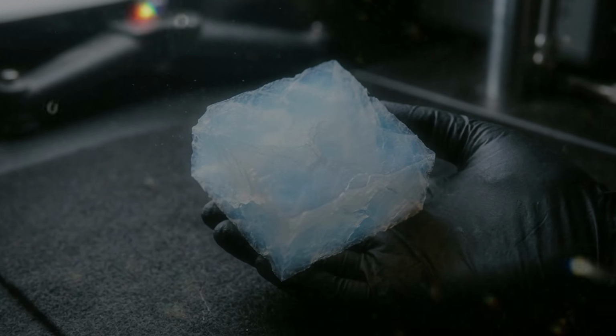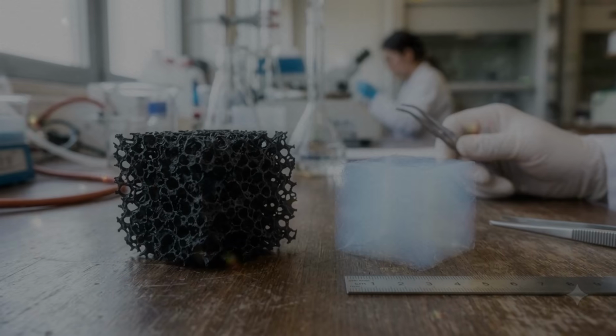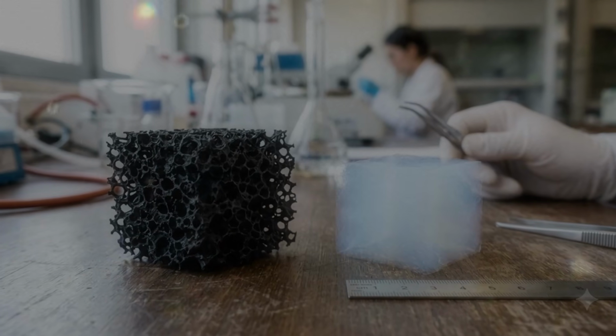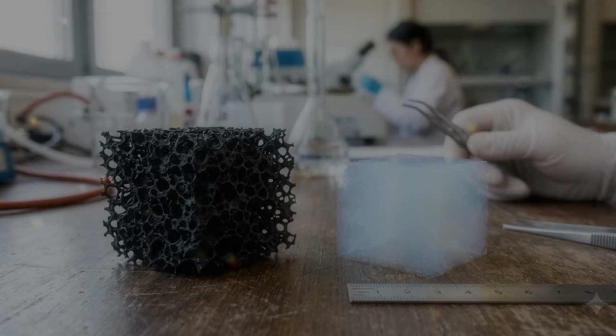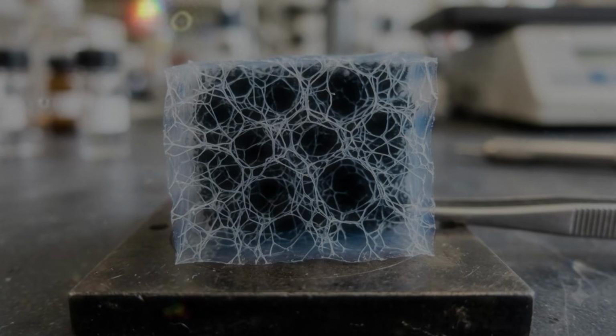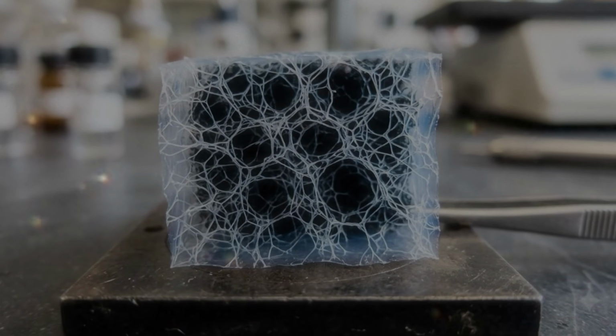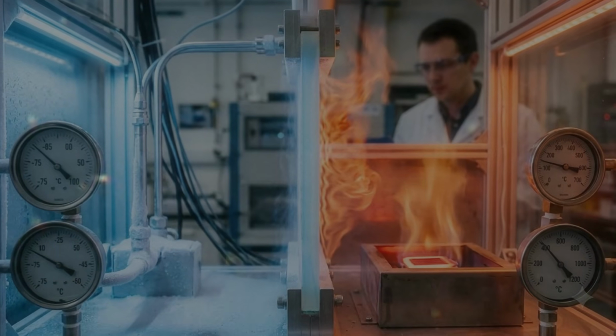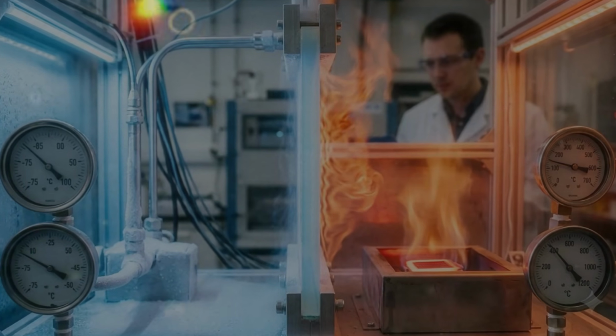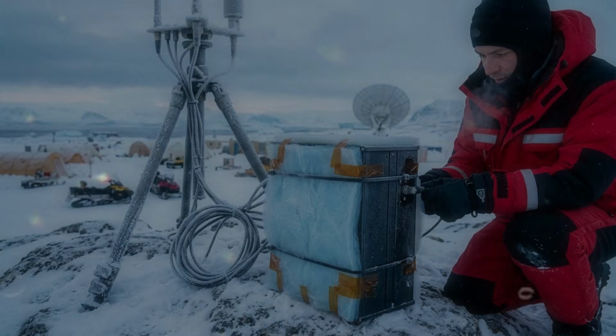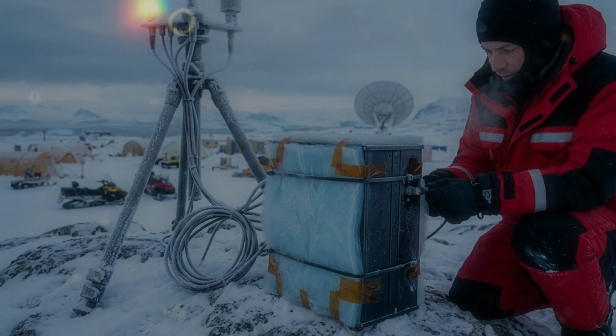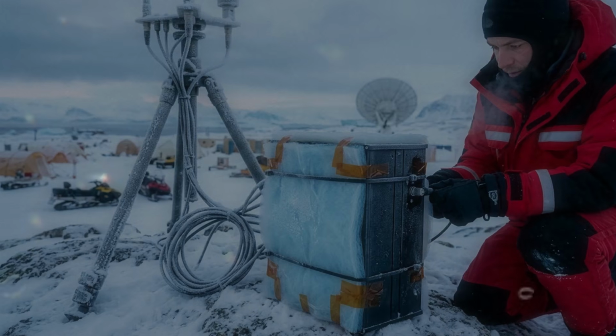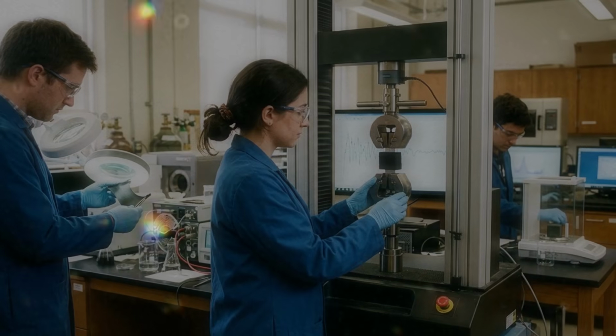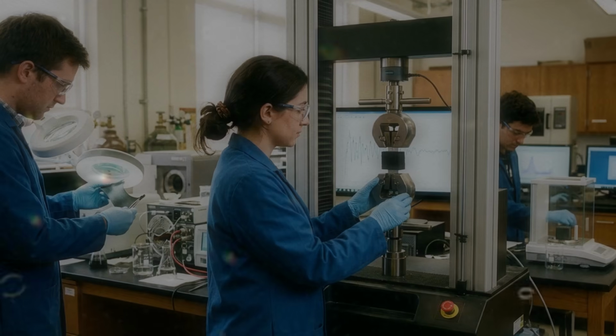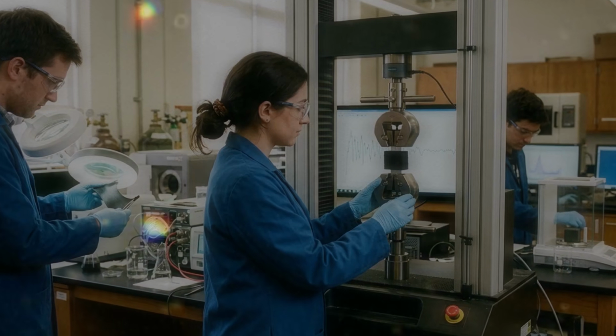Fire behavior creates another challenge. Silica aerogel does not burn easily because silica is already a stable oxide. It can tolerate high temperatures, although its structure may change or shrink under extreme conditions. Graphene aerogel is made from carbon and can burn in the presence of oxygen if it becomes hot enough. The open pores expose a large surface to the air, which may allow the reaction to spread quickly once it begins. Fire-resistant coatings, mineral additives, or protective layers can improve safety. These additions may also change weight, flexibility, and electrical behavior.